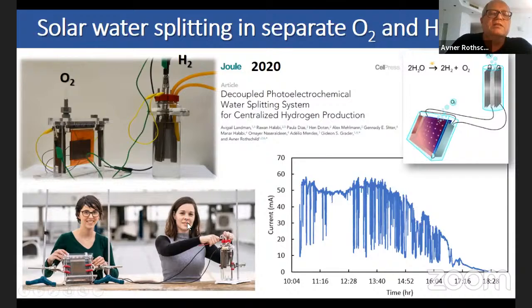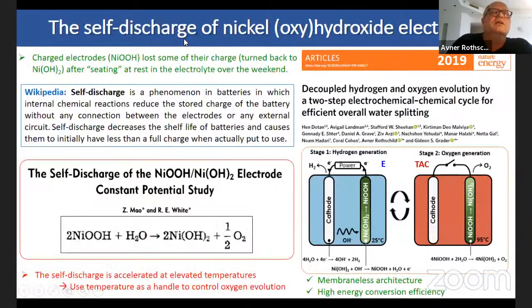So Avigail, my PhD student who was working on this concept, noticed that if she left the charged electrodes over the weekend and came back on Sunday, the charged electrode had lost some of its charge. And then we checked why this happens. And we discovered that this is simply the well-known phenomenon in batteries called self-discharge, which is basically this reaction: a charged nickel oxyhydroxide electrode can react spontaneously with water and get discharged, or regenerated, while emitting oxygen. So in principle, this can save us the swapping of the electrodes.